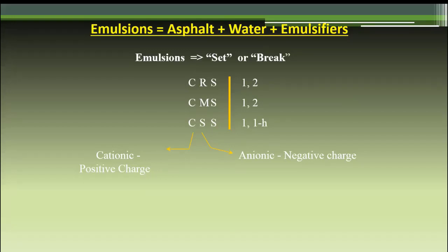How long will it take the different cutbacks and emulsions to be able to pave over in relation to each other? Maybe the set time or cure time. Yeah, cutbacks, again, if you look in the spec book, standard specifications, when you're shooting MC for a prime, most states dictate a curing period, 72 or 96 hours, 3 or 4 days. And that's because you're trying to evaporate diesel fuel. Well, the more diesel fuel you have in it, the lower the grade of the MC, the longer it's going to take. But temperature, humidity, time of year, all impact that. But in general, 3 to 4 days is probably a pretty good rough rule of thumb on MCs.